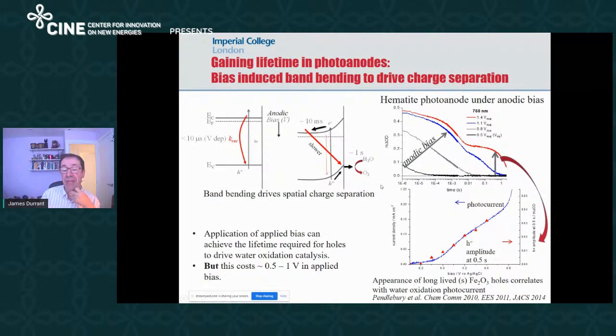And you can see that experimentally. If you apply a positive potential to hematite and look on long time scales, microseconds to seconds, with potentials which are not very positive, you just have a small decay of trapped charge in the hematite. But as you apply a more positive potential, you generate the band bending, you drive the holes to the surface, the electrons to the bulk, and now you gain lifetime. In particular, you can generate this very slow decay phase with a decay time of around a second, which is the holes getting to the surface and driving water oxidation. And indeed, the amplitude of this slow decay phase correlates rather well with the current you measure as a function of voltage.